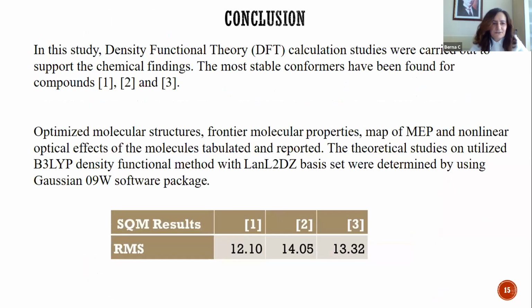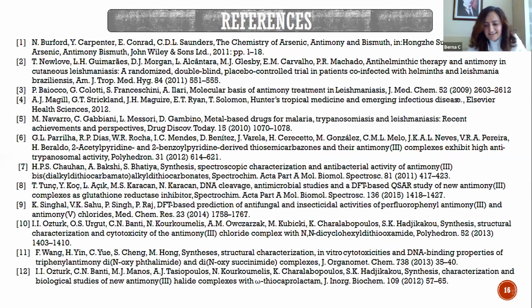And then the conclusion. In this study, density functional theory DFT calculations were carried out to support the chemical findings. The most stable conformers have been found for compounds 1, 2, and 3. Optimized molecular structures, frontier molecular orbital properties, maps of the molecular electrostatic potentials, and the non-linear optical effects of the molecules are tabulated and reported. The theoretical studies utilized the B3LYP density functional method with the LANL2DZ basis set, determined using the Gaussian 09 package, and the SQM result is also here, and here is my reference.